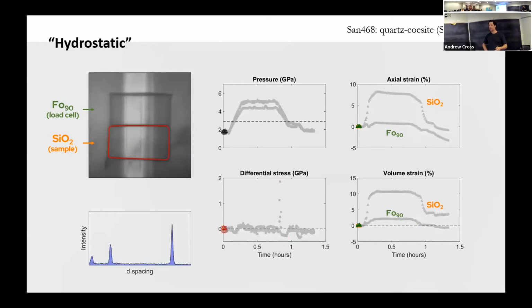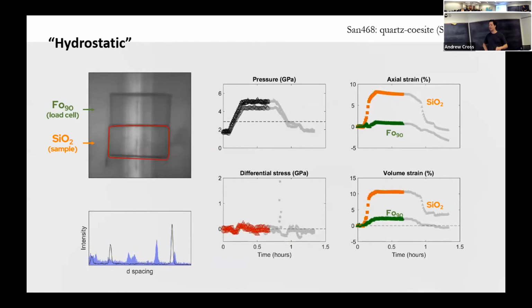Maybe I'll just play that through again. So you look, there's a small amount of volume decrease in the SiO2 sample that you'll see. And then as we go through and start ramping back down, you'll see that the sample expands again. Here it goes. And it starts out exactly the same dimensions that it was at the beginning of the test. Although, yeah, I guess there is a small volume decrease that it's difficult to see on this.